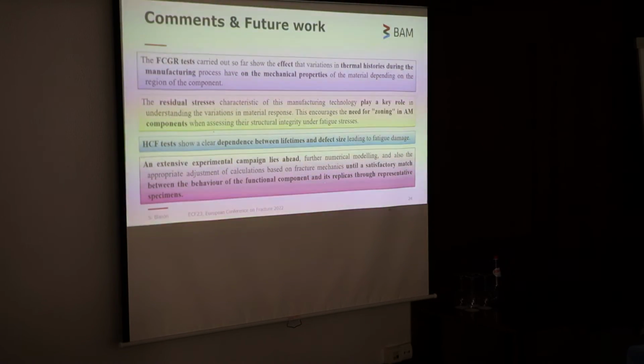So, as a summary, we can say that the thermal histories during manufacturing play an important role in order to characterize the materials, and also the residual stresses in different positions make it difficult to have a general idea of the behavior of the material. That's why we think it's very important to zone the component in order to evaluate the most risky area. And apart from that, it's clear that in terms of the high cycle fatigue results, there is a clear dependence between the lifetimes and the defect sizes.